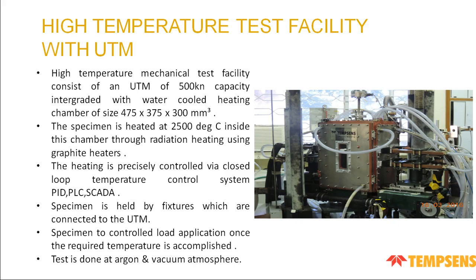The specimen is heated at 2500 degrees centigrade inside the chamber through radiation heating using graphite heater. So this is basically testing of material at very high temperature, 2500 degrees centigrade, and the material is heated through graphite heating elements by radiation, and the heating is precisely controlled by a closed loop system or PLC SCADA system.